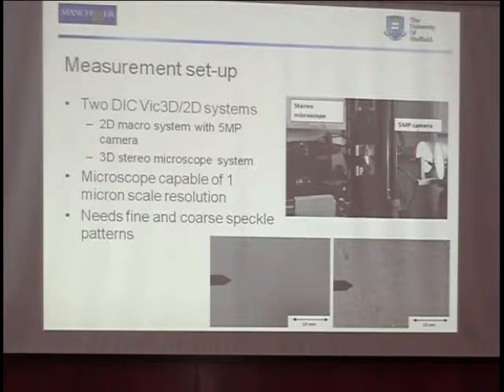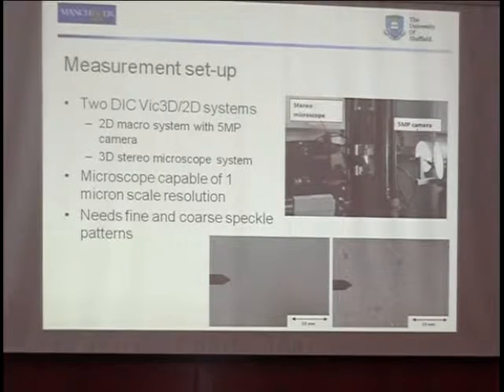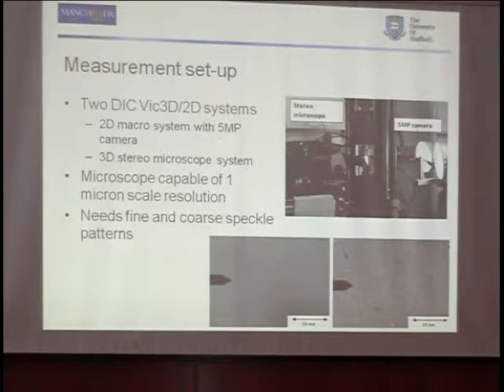Obviously, this was discussed with Pablo last night over the speckle patterns. The speckle pattern requirement is quite different. These two images down here show the speckle pattern requirements for the front and back face, if you like, of the specimen. This is for the macro one, this is for the 2D. And this is viewed on the same scale, but for the microscope measurement. In terms of speckle size, each speckle is in the region of 3 to 5 microns, and that's in the region of 10 to 20 microns.